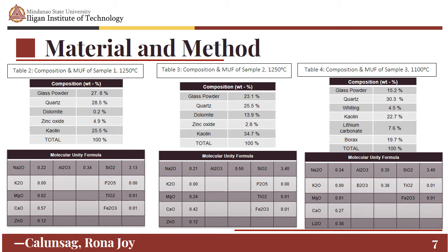So for the molecular unity formula, the Na2O is 0.34, K2O is 0, MgO is 0.01, CaO is 0.27, Li2O 0.38, the Al2O3 0.35, B2O3 0.38, and for the SiO2 3.40, TiO2 is 0.01, same goes for Fe2O3, which is 0.01.